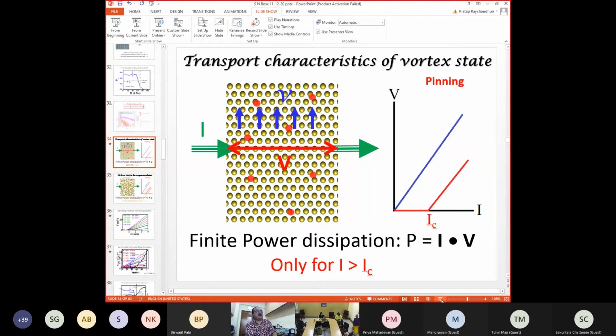On the other hand, if I have pinning, then these few pins, in the case of a vortex solid, will pin this entire vortex solid here. So now this current will apply a force on the vortices, the Lorentz force, but this vortex lattice will not move till I reach some current which is the critical current where it overcomes this pinning force. And now I will have again dissipation, then the slope will be roughly similar. What happens if I have a vortex fluid?